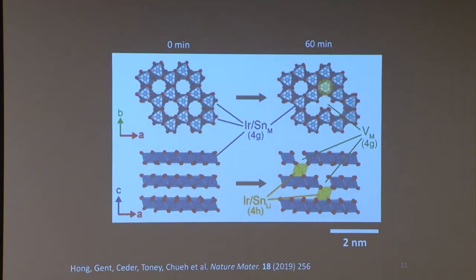And it doesn't stop here. The heterogeneity extends all the way to the atomic level. So now if you look at the scale bar, 2 nanometers, and look within the crystal structure, it's also heterogeneous there. The material doesn't have the perfect crystal structure. It has actually a very atomically heterogeneous structure with atoms residing on the wrong position. So these are defects in the material.